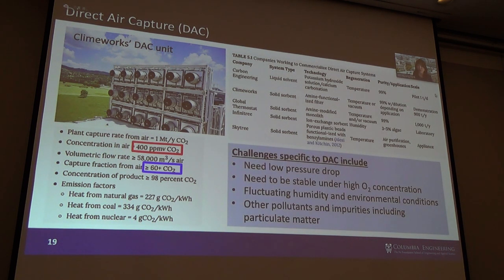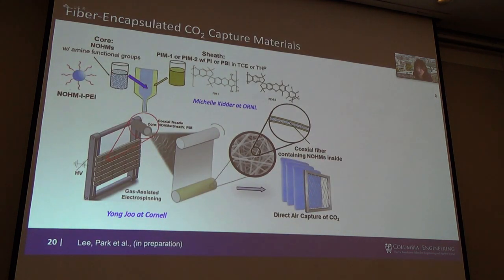Another challenge, different from point source capture, is that we really need a low pressure drop, and the material needs to be really stable under high oxygen concentration because it's in oxygen and air. And there will be fluctuating environmental conditions, some rainy days, some hot days, some dry days, and we have to deal with all of those during our operations. Going back to our NOHMs material, I love the fact that it has zero vapor pressure. We can leave a cup of NOHMs outside and it won't evaporate for years and years. It would be fantastic. But the challenge is that our NOHMs materials are highly viscous and also very sticky, so they will collect all the dust outside.